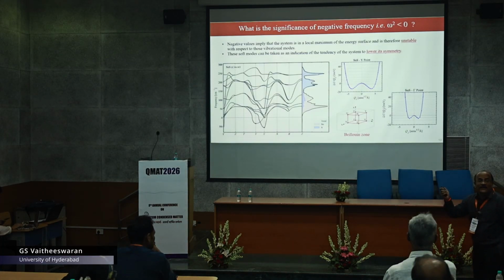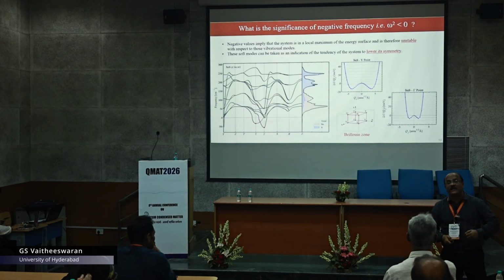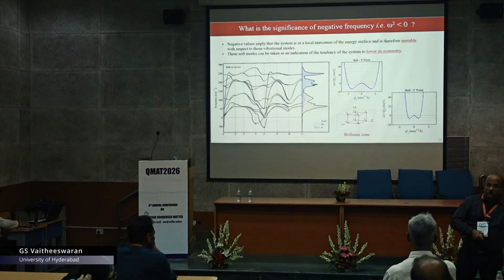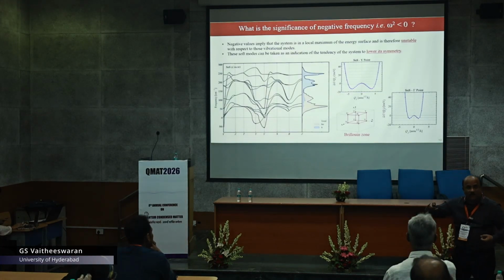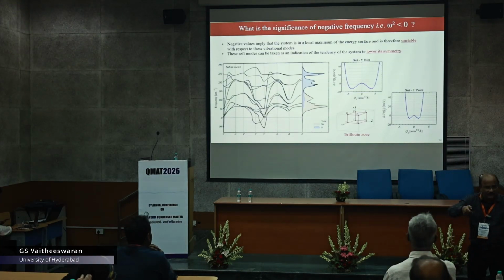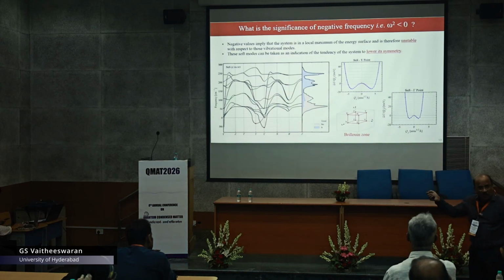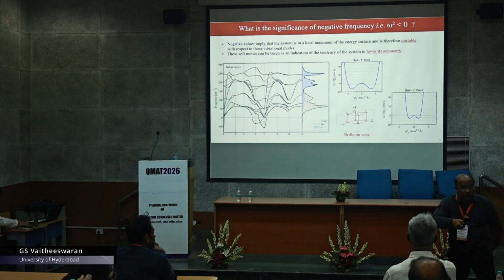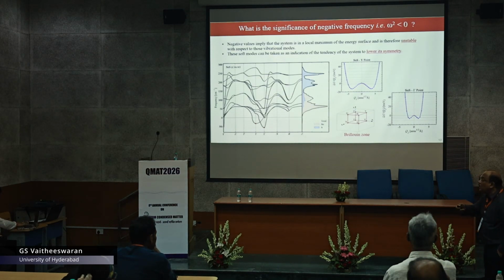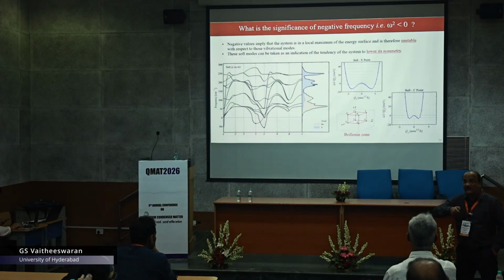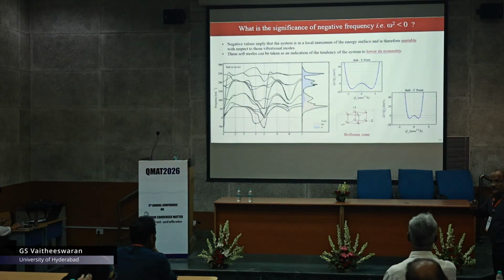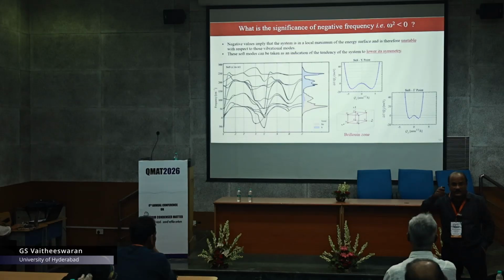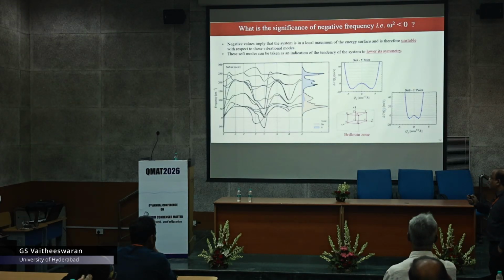And this is particularly interesting in the case of ferroelectrics, where we have a high symmetry non-polar to polar transformation, which is purely driven by temperature. And then by using this harmonic approximation, which is not so good, which has to be taken with a pinch of salt, we can still try to address some of the experimentally observed transformations, which I did with Surajit Saha from IISER Bhopal for some of the perovskites.